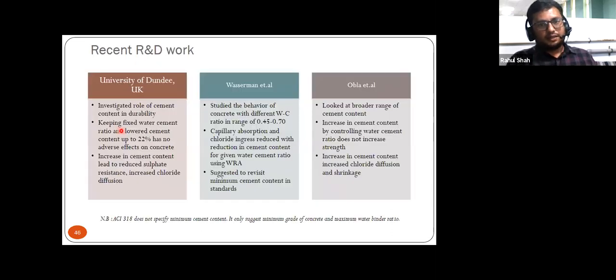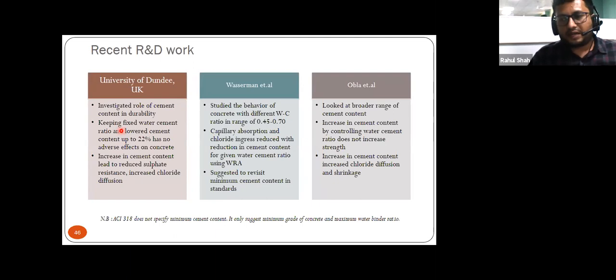If you talk about leading research and development across the globe, then these three, I guess, will be sufficient to understand the real concern of what we are lacking. First, a study investigated the role of cement content in durability. They kept the water cement ratio fixed and lowered the cement content by up to 22 percent, which had no adverse effect on the concrete, right? So our traditional thought process of using more cement has vanished. I'm reading this out: an increase in the cement content leads to reduced sulfate resistance and increased chloride diffusion, right? That is the reason we cannot use super sulfated cement in the marine zone. It increases the chloride diffusion, right?